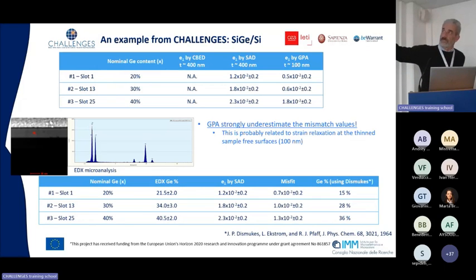And what are the results? This is the nominal germanium content. By convergent beam, not applicable. By diffraction, 1.2, 1.8, 2.3, and by GPA, that is analysis in high resolution in thin samples, 0.5, 0.6, 1.8. Much and much lower, because analysis in diffraction mode was performed in a sample 400 nanometers thick. Analysis by GPA was in a sample 100 nanometers thick.